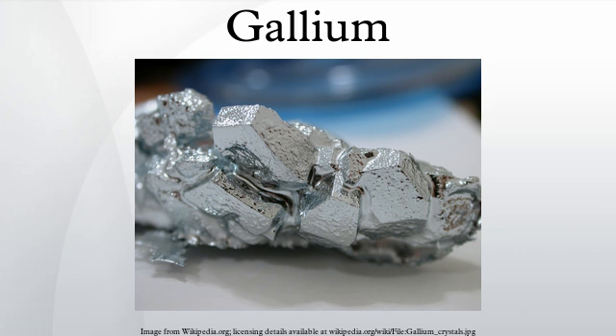acceptance. Because gallium wets glass or porcelain, gallium can be used to create brilliant mirrors. When the wetting action of gallium alloys is not desired, the glass must be protected with a transparent layer of gallium oxide. The plutonium used in nuclear weapon pits is machined by alloying with gallium to stabilize its delta phase. Gallium added in quantities up to 2% in common solders can aid wetting and flow characteristics. Alloys of Al and Ga have been evaluated for hydrogen production. It is used as the alloying element in the magnetic shape memory alloy Ni-Mn-Ga.